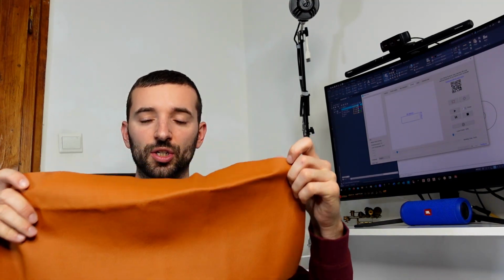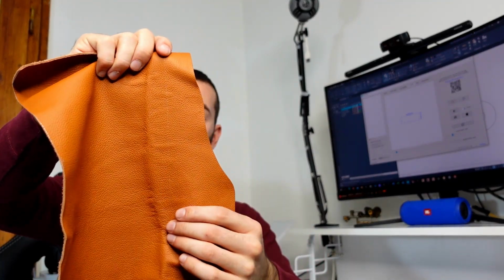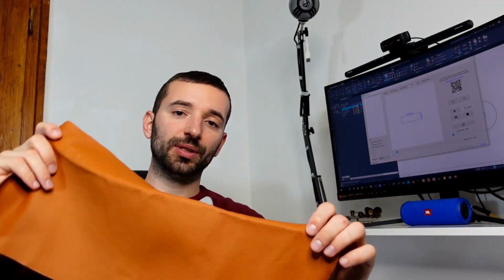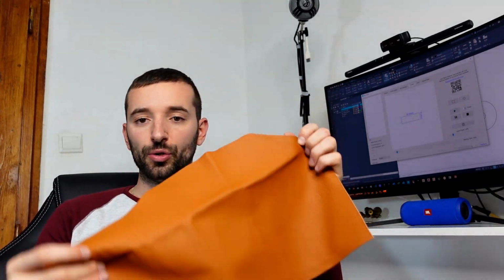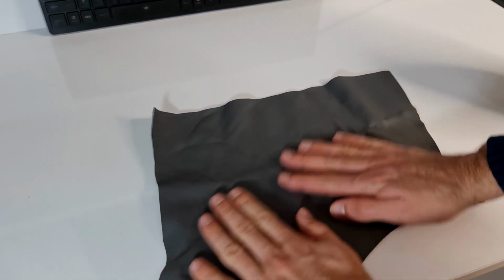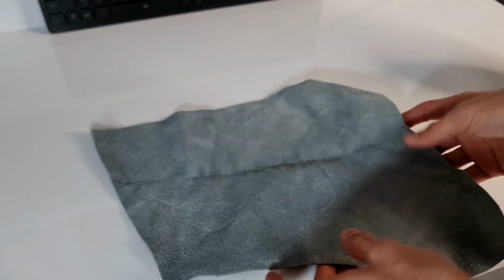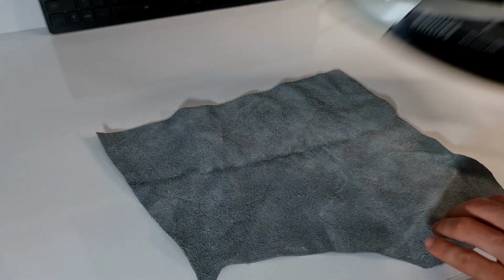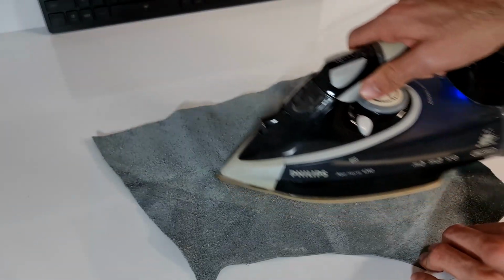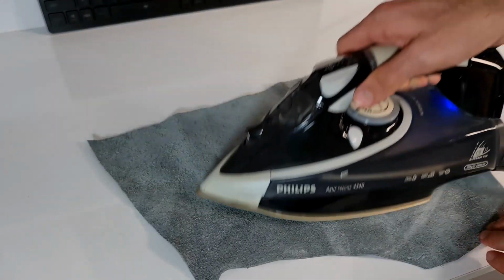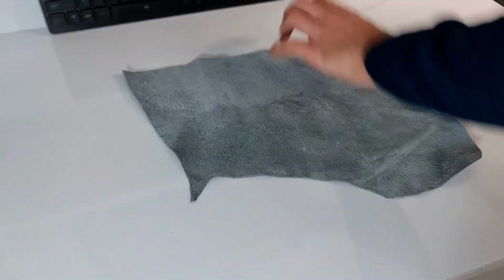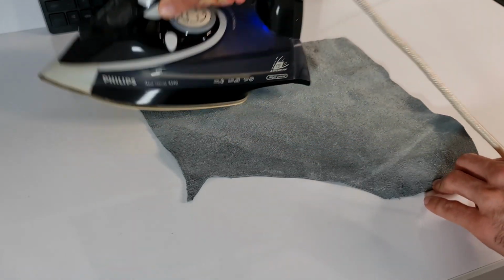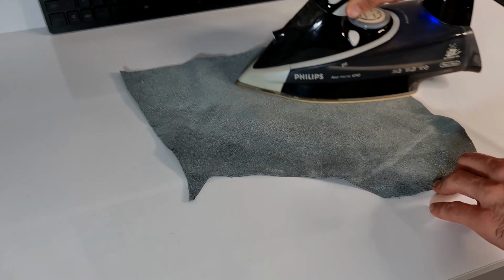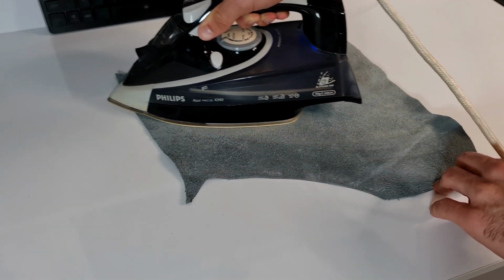Now, something that I found particularly important when working with leather is that you want your leather to be as flat as possible. So if you have any creases or folds, you want to get rid of that. And one way you can do that is to use a typical iron. So you'll put this on a flat surface like a desk or your ironing board if you have one, and then iron it. I would recommend ironing always from the fluffy side, from the corium side, because ironing from the grain side might end up discoloring your leather if it's tinted like this one, and also you might end up burning it. So it's something that you want to pay attention to.